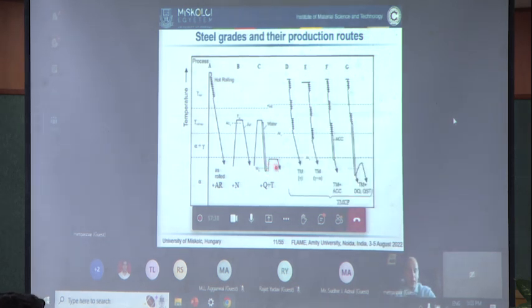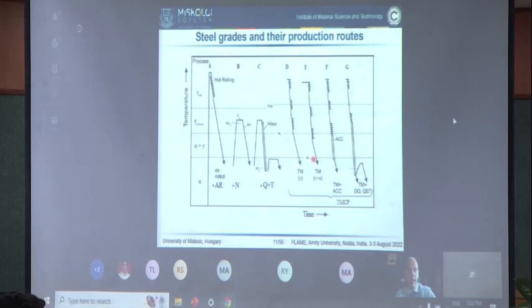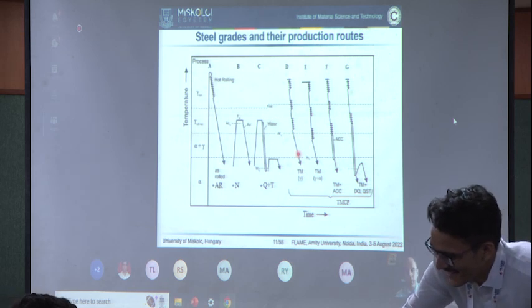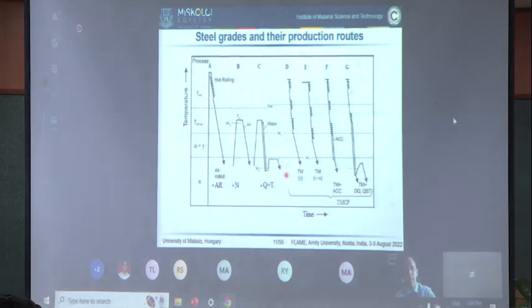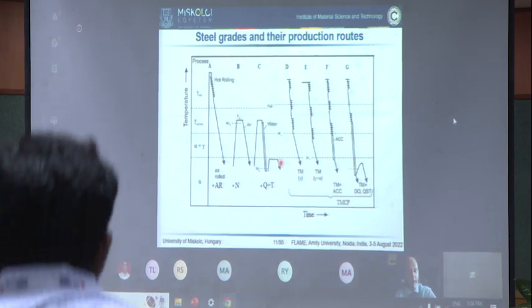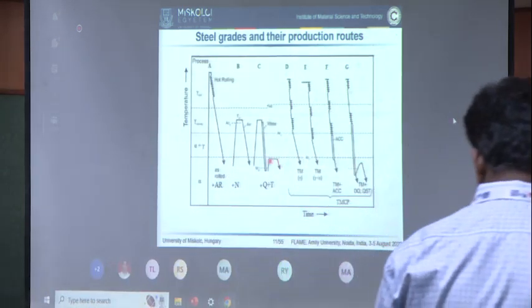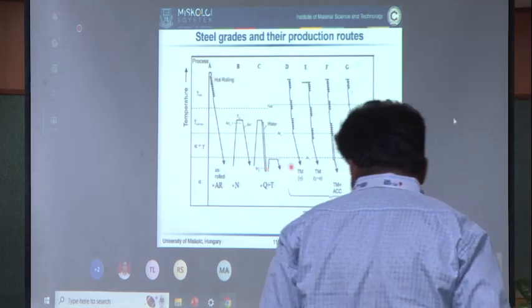Therefore, water cooling is used, which is followed by a high temperature tempering under the A1. We get a kind of martensite after water cooling, and then make tempering in order to make a more equilibrium microstructure with some carbide precipitates. This is generally called spheroidite.